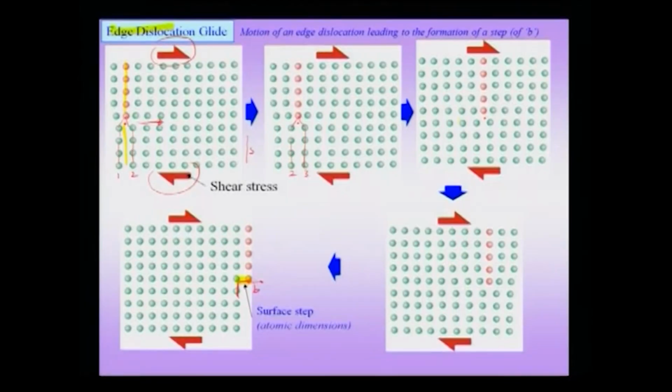But in the case of nanocrystals, it is important to note that this energy formula is not valid anymore, because the presence of the dislocation can actually lead to the deformation of the crystal itself, as we noticed before. Now, when I have an edge dislocation in a crystal, I can think of it as an extra half plane.